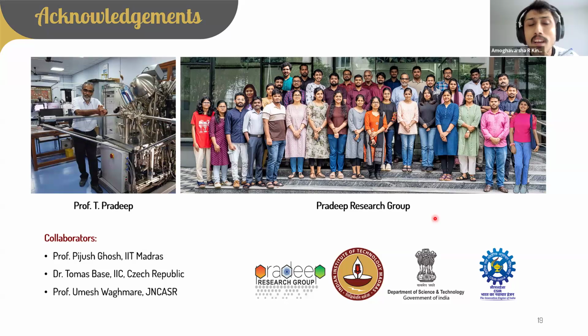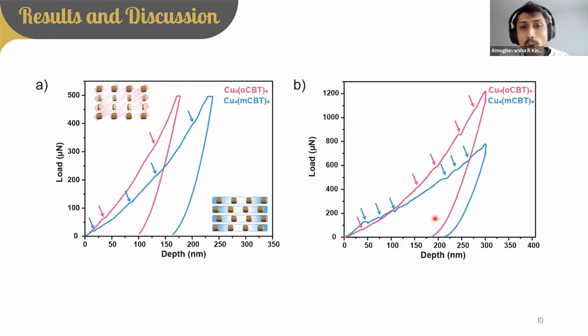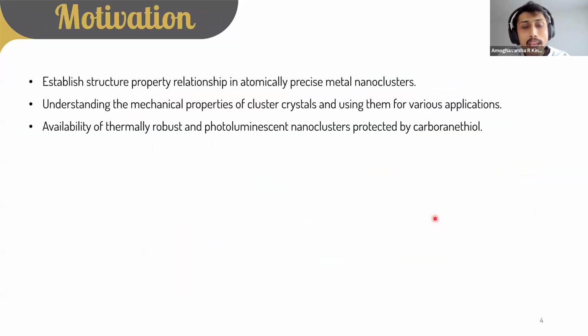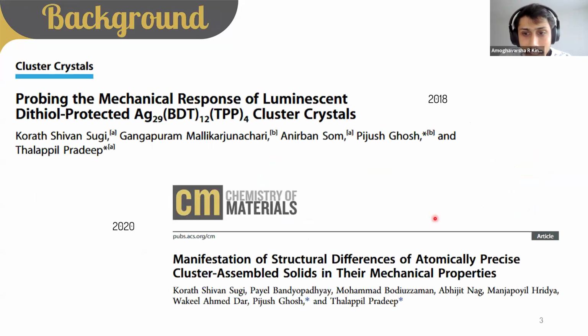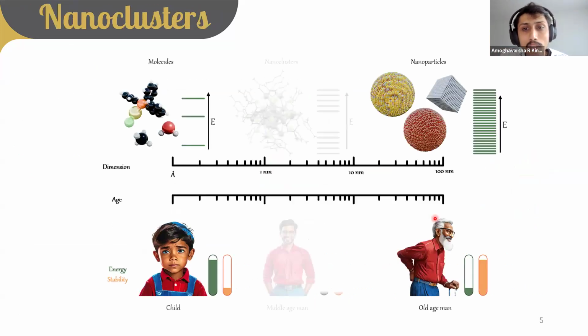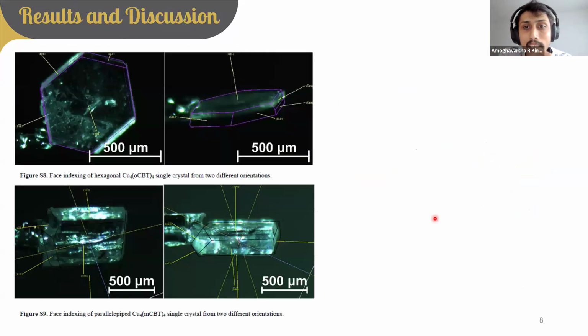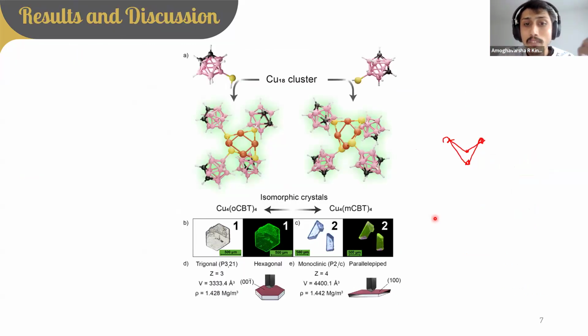Okay, copper complexes I have not come across till now, but metal complexes usually have different kinds of ligands which have different kinds of interactions. Even then, if we take copper complexes, they usually have organic thiols. In the background study, I showed these Ag29 clusters which also use organic thiols. They have pi stacking and all, but their strength is in the range of 3 to 5 gigapascal only. But this copper nanocluster, which is protected by carborane thiol, is showing higher strength. Mainly, we think it is because of the rigid carborane cage, which is protecting the metal, and also the very small size of the cluster as well.